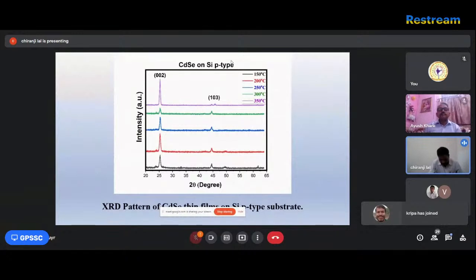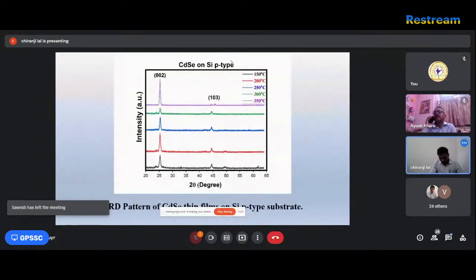XRD pattern of CdSe thin film on p-type silicon substrate. XRD diffraction patterns were recorded in the 2 theta range of 20 to 65. Identification of crystal structure phases and lattice planes for the observed diffraction peaks from the atomic planes of the deposited thin film. The XRD pattern also highlights the high intensity peak 002 at 2 theta 25.23, and another peak is observed at 44.58. As the substrate temperature increased from 150 centigrade to 350 centigrade, a new peak is observed. The crystallinity of the thin film also changed with the temperature.